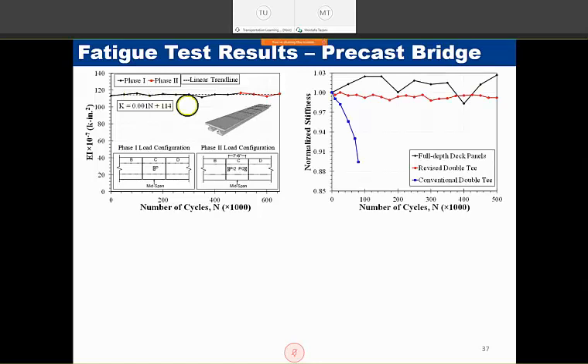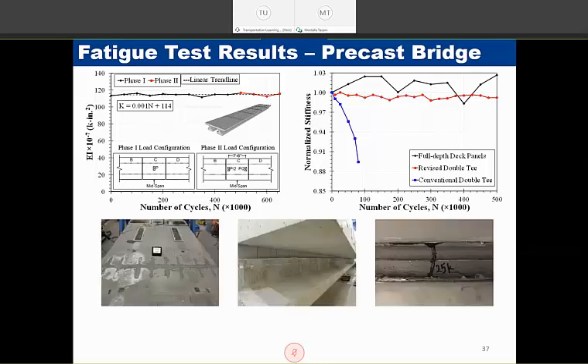And if we want to compare the overall stiffness of this fully precast bridge with double T, which is the blue line here, you can see that in the conventional double T bridge, the joints deteriorate very fast, even in less than 100,000 cycles of fatigue testing, while the proposed option has basically constant stiffness, and the stiffness didn't actually deteriorate. So it was a better option than the conventional double T bridges that are currently used in practice in terms of basic service performance.